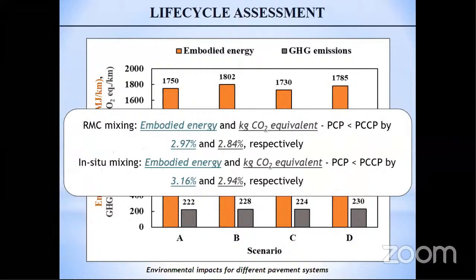for RMC mixing, the embodied energy and carbon dioxide equivalents of pervious concrete pavement were lower than those of Portland cement concrete pavements by about 3%. Similarly, for in situ mixing as well, the embodied energy and carbon dioxide emissions for pervious concrete were lower than Portland cement concrete by 3%. This reduction may basically be attributed to the lower amount of cement which was required for the development of the pervious concrete layer.